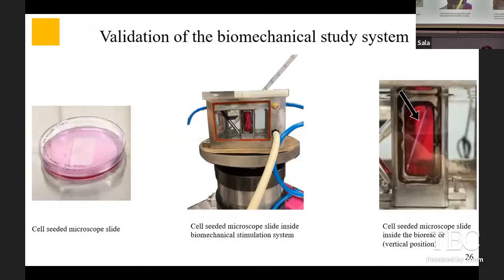Now, as for the validation of the biomechanical study system, first, we wanted to validate the system by itself. And by this, I mean, we didn't use the scaffold because the scaffolds are tricky. We used a microscope slide that is a known substrate. And we didn't do any mechanical loading. So for this test, what we did was we cell seeded a known substrate, a microscope slide, and placed it into the mechanical stimulation system by itself. Here you can see it in this picture.